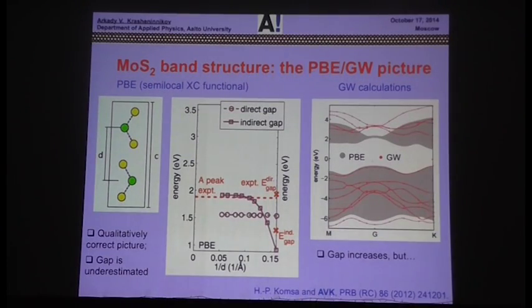If you take the standard approach, density functional theory with local and semi-local exchange correlation functionals like LDA or GGA, and calculate the dependence of the direct and indirect gap as a function of separation between the layers. Basically, when we are here, this means you have an isolated single sheet, and there you have a stacked material, and then you start increasing the separation between the layers. So essentially, you have a nice transition from indirect to direct band gap, and as usual with conventional DFT, the gap is a bit smaller than in the experiment, but overall agreement is fine.